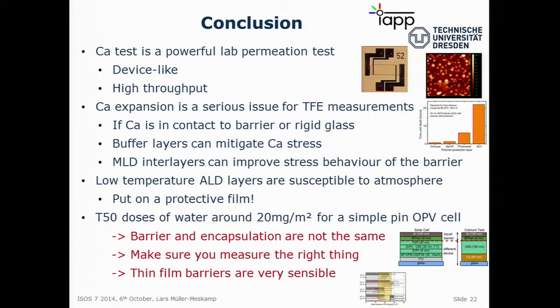A bit special is that the calcium expansion is a serious issue for the thin film encapsulation measurements, especially in these cases. And what's interesting is that the MLD can mitigate the stress a bit. Low temperature ALD is needed for thin film encapsulation, because you cannot do a hot ALD process on top of your devices. So low temperature in our case was 100 degrees or 80 degrees in between. You have to protect it, put on a protective film.